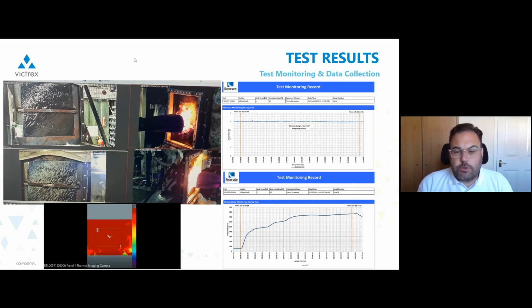And what you see at the bottom, this is exactly what I talked about before in the previous slide. This is the temperature of the rear face from the thermocouple that's at the rear face. Everything is in Fahrenheit, and you can see we start around room temperature, and within five minutes or so, we get up to 800 or 900 F. Next slide.